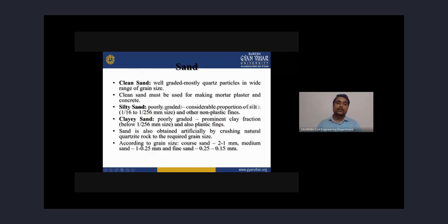According to composition, there are clean sand, silty sand, and clay sand. Clean sand is well graded with mostly quartz particles and a wide range of grain size. Clean sand must be used for making mortar, plaster, and concrete. Silty sand is poorly graded with a considerable portion of silt. And clay sand is poorly graded with a prominent clay fraction below 1/256 mm size. There is also artificial sand. Sand is also obtained artificially by crushing natural rock to the required grain size.